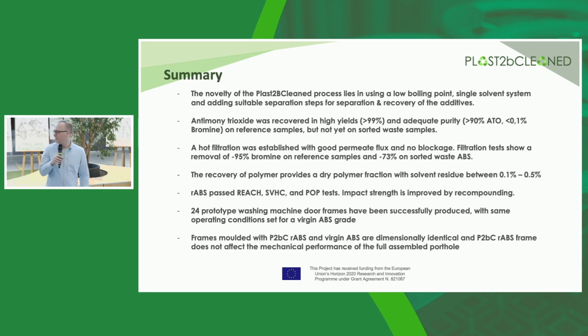Of solvent recovery, sorry. I will just add on this one. One of the additional drawbacks of using anti-solvent to precipitate the polymer solution is that at the end of the process, you need to separate a mix of two solvents. And the goal of our process is to be also energy efficient and possibly economically viable. If you need to separate two solvents, it leads to higher energy needs. So that was also one of the aspects why we chose spray drying as a final processing step.